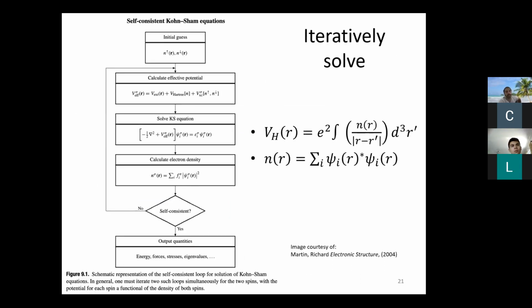And this is solved iteratively. Basically, you guess the charge density. You can literally just apply an atomic density on each of the ions, and then you calculate an effective potential, which is dependent on the charge density. From that, you can plug it into the Kohn-Sham equation to get a wave function. From that wave function, you could then get the charge density, as it's the wave function squared. It gives you the probability of the electron density. And from that charge density, you could then start this iteration process over and over until the charge density and the wave function don't change much. Then from whatever you get at the end, you could calculate energies, forces, stresses, and a bunch of other eigenvalue problems for the system.